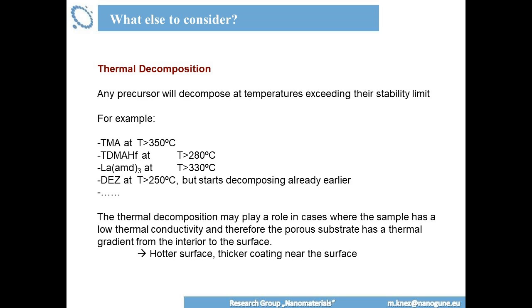So thermal decomposition plays a role as well, especially also with DEZ. People think diethyl zinc is such a thankful material. It's actually not. It decomposes quite early, so this is the literature value. It starts decomposing also earlier already. There is a reason, if you think about the literature, what it says about the ALD growth cycles with aluminum oxide and zinc oxide and diethyl zinc and so on. Diethyl zinc is around 2.1 angstroms per cycle, while all the others are somewhere around 1, 1.2, 0.7, 0.8.